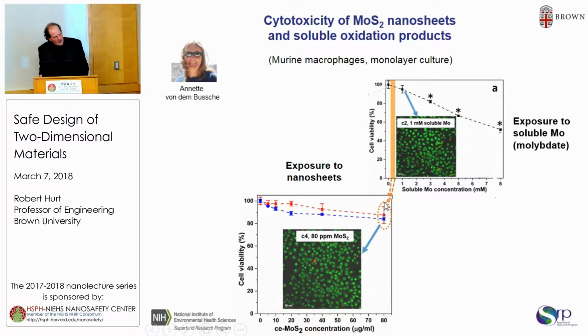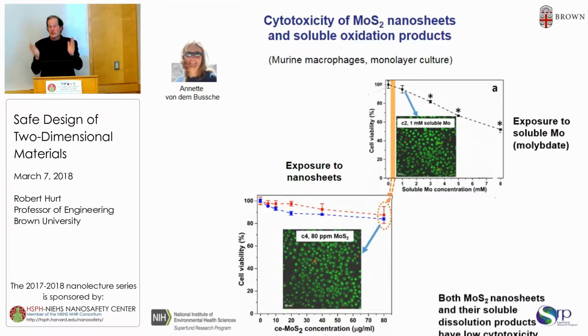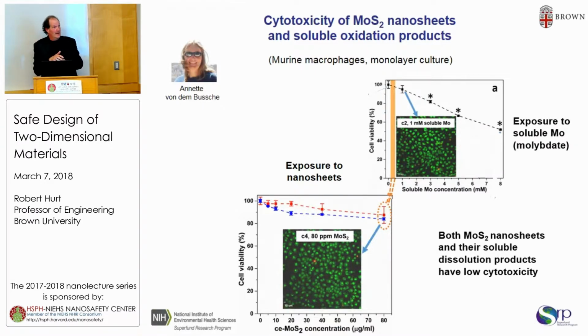But this top dose here of 80 micrograms per mL, if you convert all of that to the soluble ion, that corresponds to this concentration. And this material then is non-toxic at doses we would normally consider in nanotox studies. So MoS2 is a nice material. Both the nanosheets and their soluble products seem to have a low cytotoxicity. And at least for this material, we might also set it aside as a somewhat lower priority case for detailed